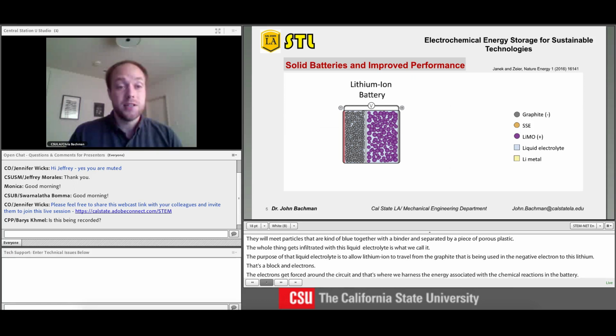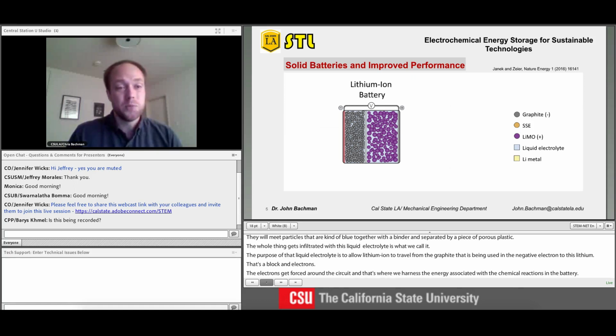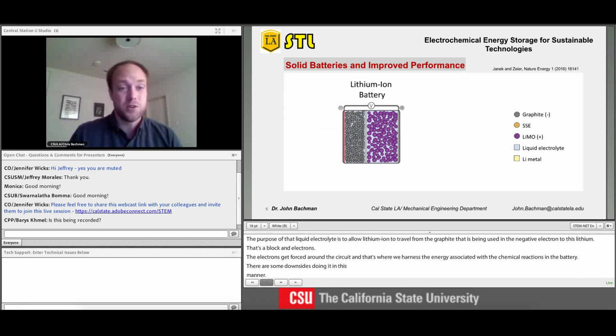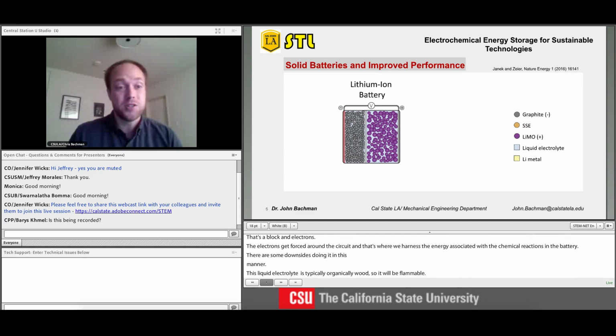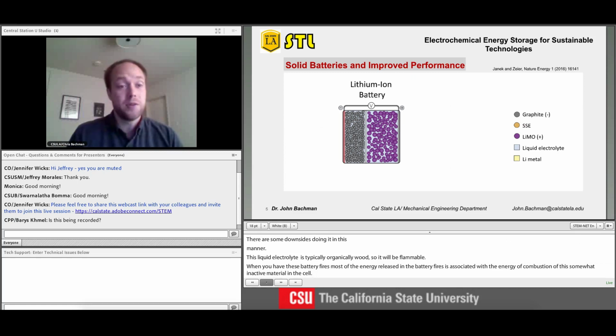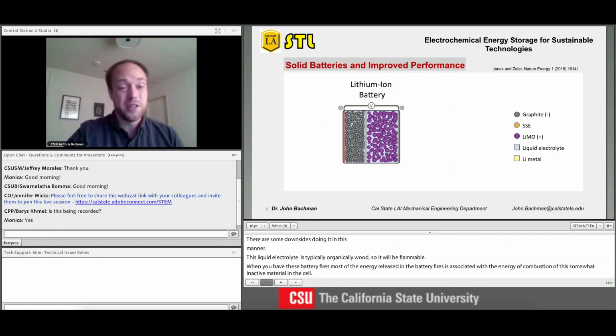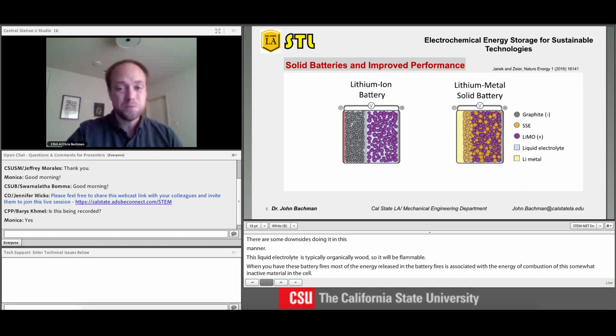This liquid electrolyte is typically an organic liquid, so it'll be flammable. And so when you have these battery fires, most of the energy released in these battery fires is associated with the energy of combustion of this somewhat inactive material in your cell. The other downside with this current technology is that you are forced to use graphite instead of lithium metal, which offers the promise to have large increases in the energy densities of the cell.